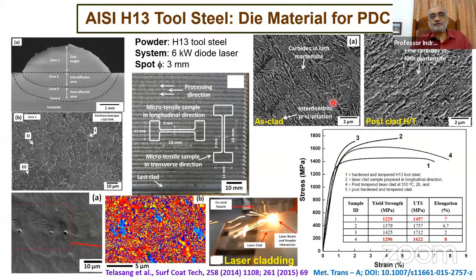So now let me refer to some activity we did nearly 8 years ago. Gururaj Telasang was our PhD student at Kharagpur. He's now a senior scientist in ARCI Hyderabad. Gururaj showed something very interesting. He showed that if you have H13 tool steel, in fact, this was basically a die component for pressure die casting. So this die, when we made laser cladding with the same H13 tool steel, so H13 tool steel pressure die casting die overlaid with laser cladding.